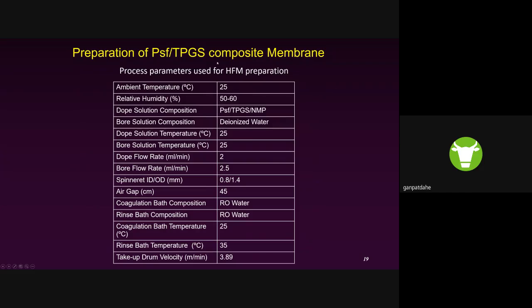So these are the typical process parameters that we use to make a hollow fiber membrane. We try to keep the temperature the same. That way, one can avoid the temperature impact, so we can make the membrane consistent. The humidity was kept between 50 to 60%. The temperature of the dope solution was also consistent, at 25 degrees Celsius, so that every time we make the fiber, it will produce the same result.